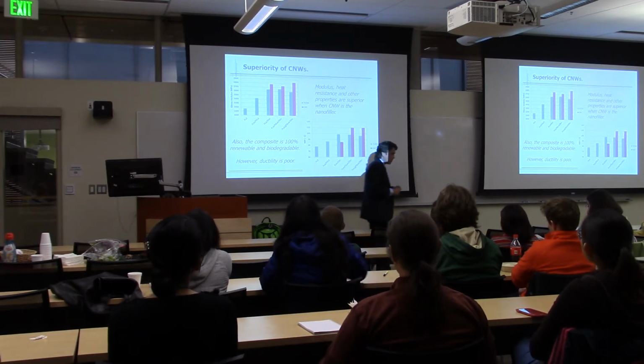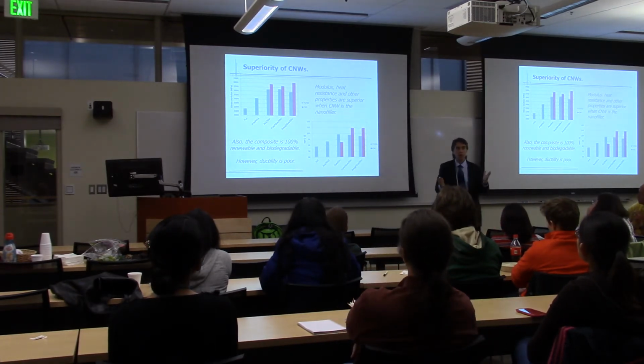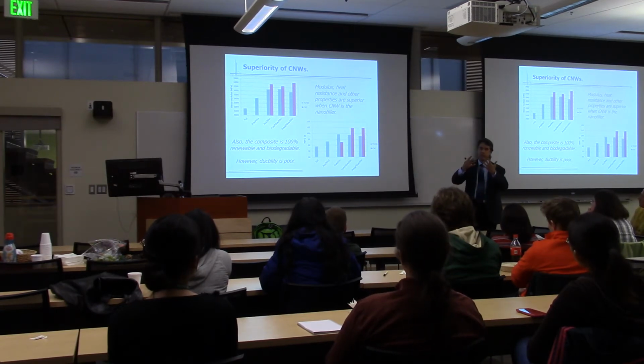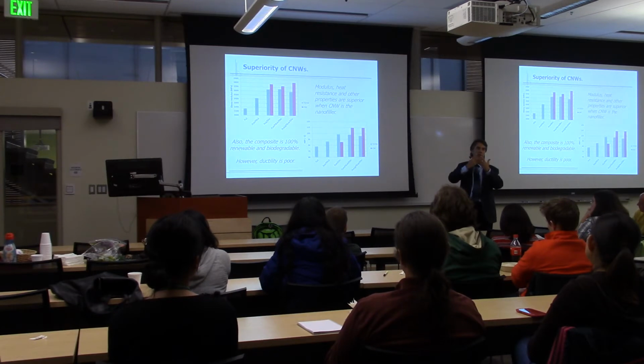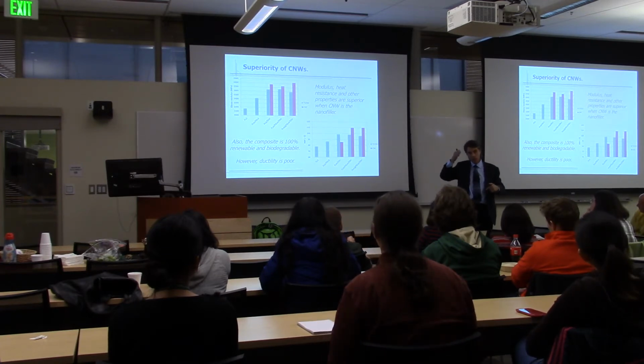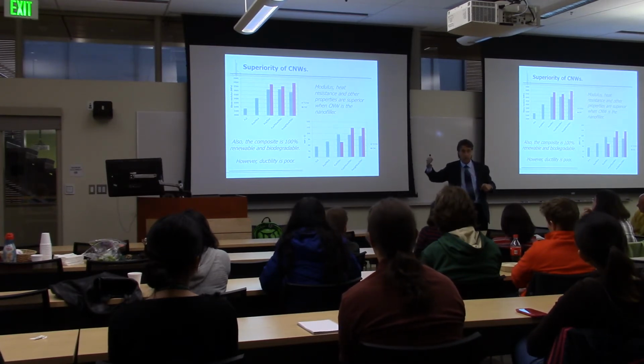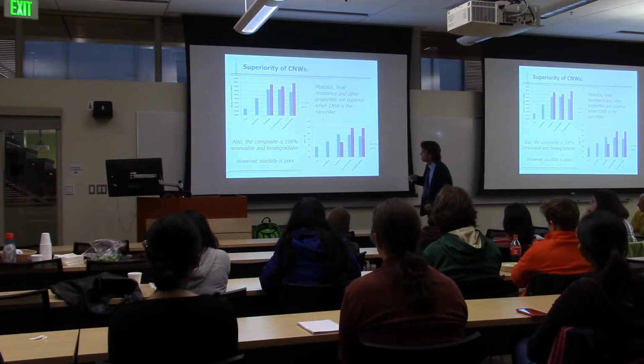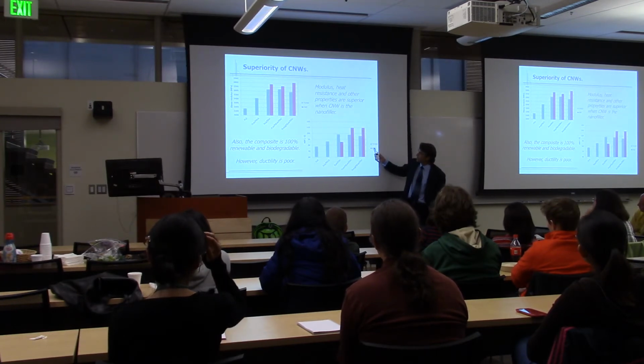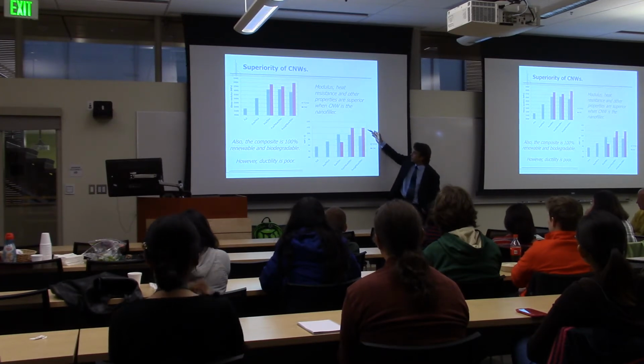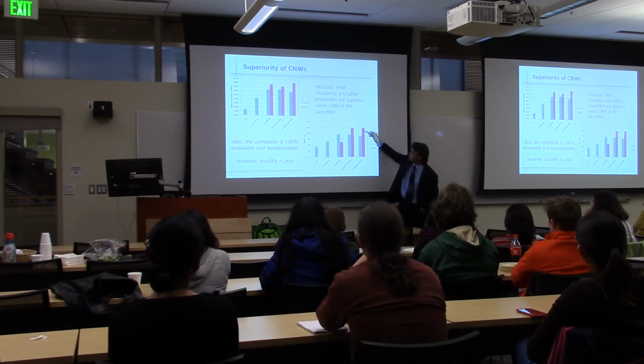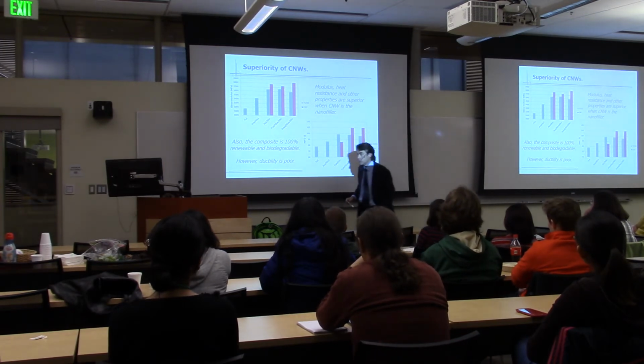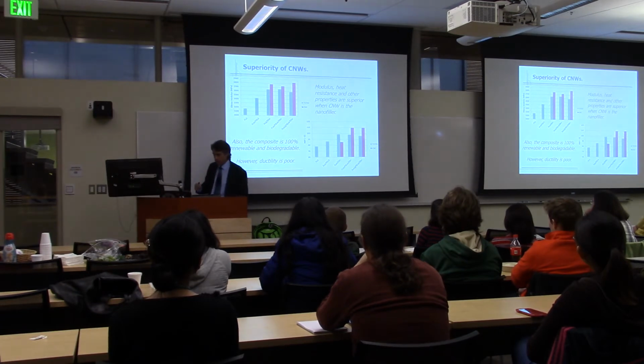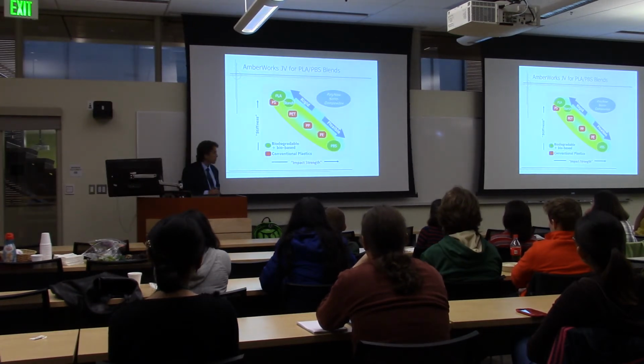And as I alluded to before, high aspect ratio fibrous materials are typically much better than spheres. The reason for that, you can think about that log jam effect. There's a percolation threshold as you go to higher and higher concentrations, and when you have long aspect ratios, the percolation threshold is dramatically pushed to lower and lower volume loadings. Here we're doing a comparison of the cellulosic nanocrystals versus the silica, and you can see at comparable volume fractions, this is about 12 degrees better in its heat distortion temperature. So nano is cool, but not all nano fillers are created equal, I guess, is the take-home message.